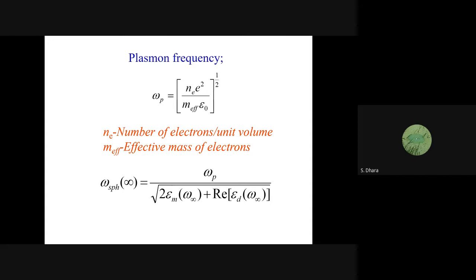And as you know, the plasmon frequency of the nanoparticles, yesterday I forgot to give this formula, is directly proportional to the root of n, the carrier density available. So naturally, a large number of electrons will largely raise this omega, the resonance frequency. And this resonance frequency is also controlled by the dielectric medium of the system, that is the epsilon of the material and the dielectric. The real part of the dielectric function has to be 0 to get the resonance. Next.